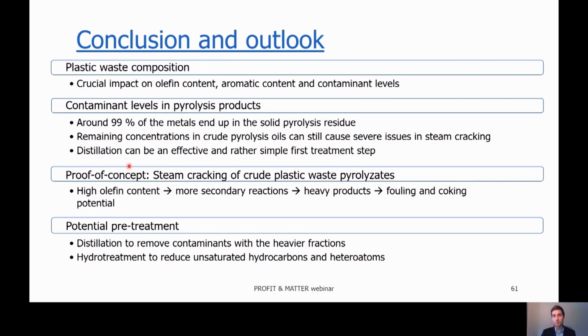The proof of concept experiments: we steam cracked crude plastic waste pyrolysates, and we have seen that the light olefin yields are quite nice. They're in a range with fossil naphtha, which is very good. However, we also see a lot of heavy products, mainly due to the high olefin content, which lead to secondary reactions, which then lead ultimately to fouling and coking potential.